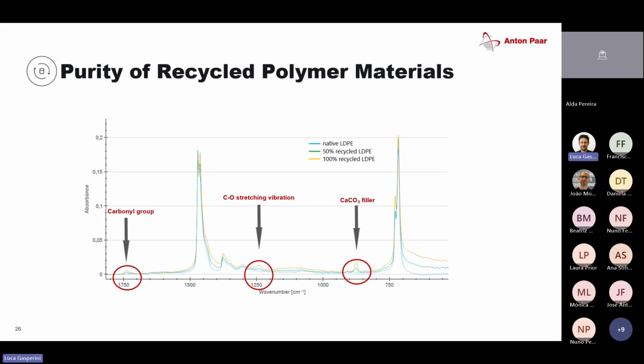So as a rule of thumb, if you don't really know how your samples behave, just take a very fresh sample and then take a very, very old one, compare these two, and then look for peaks which have changed. If I do not know which samples I'm confronted with, this is the first thing I do. I just take different times or some change, and I observe what actually changed in the product and what I see on the spectrum as well.